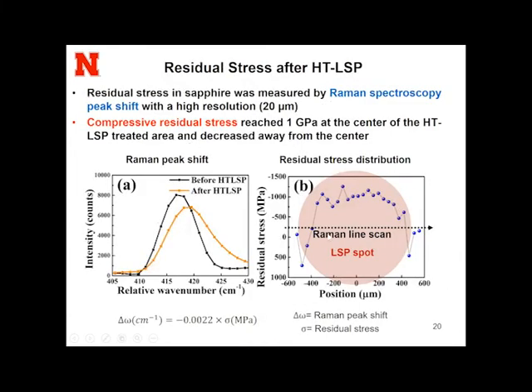So for the measurement of residual stress here, we choose Raman instead of X-ray because we found the Raman spectrum has a much higher resolution. In our system, we can have a resolution as low as 20 micrometers. So we can now measure the compressive residual stress distribution in one laser shock peening spot.